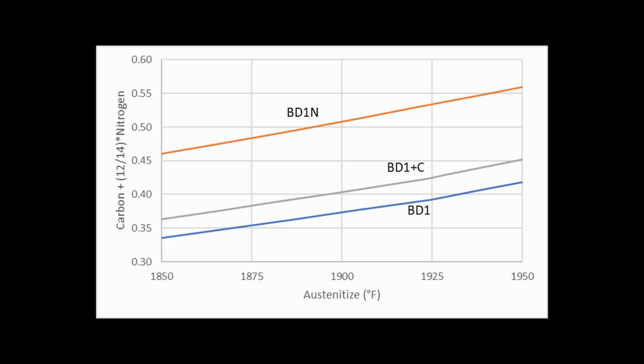adding carbon is not as effective at increasing strength as nitrogen, and that's because carbon is much more prone to forming carbides than nitrogen is to form nitrides. So if you add the 0.12 nitrogen, it'll basically all go in solution after heat treating, but the carbon is going to go towards forming more carbides, and not all of those new carbides are going to want to dissolve.